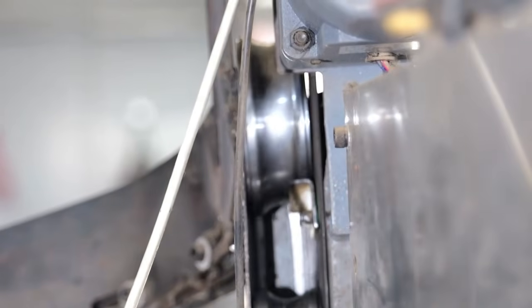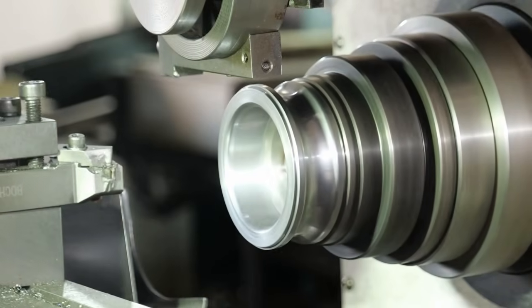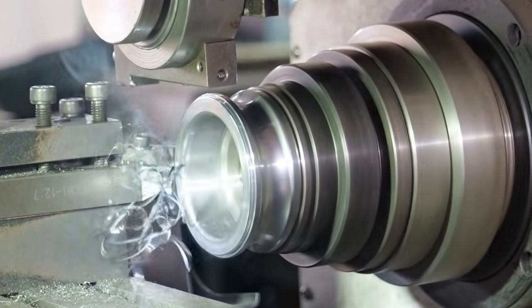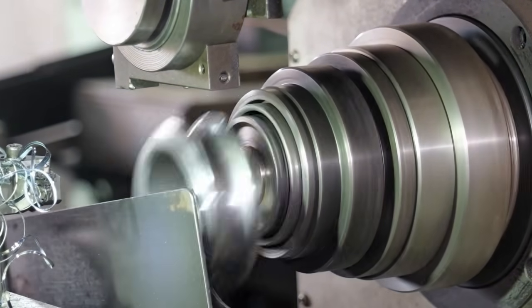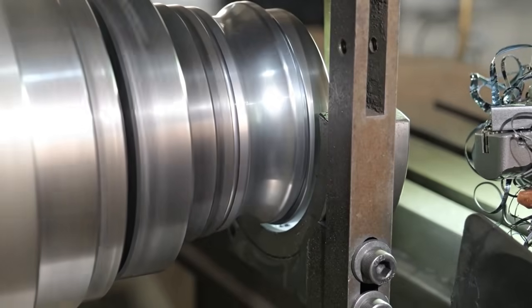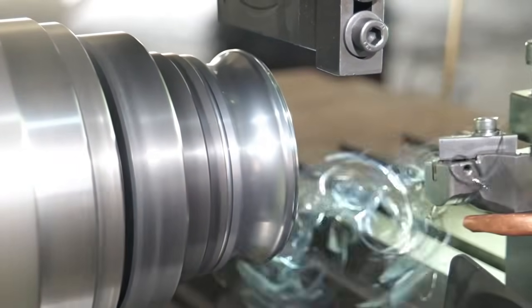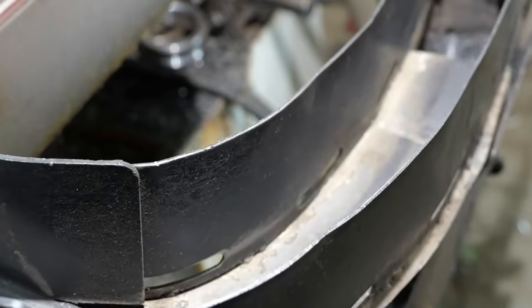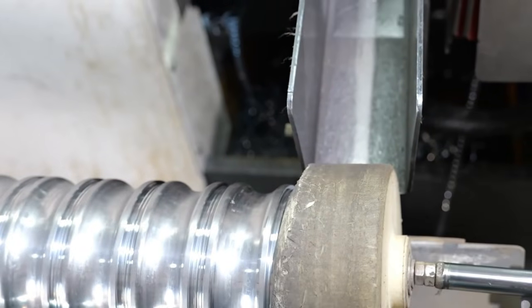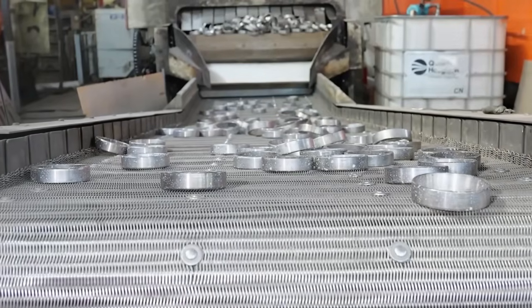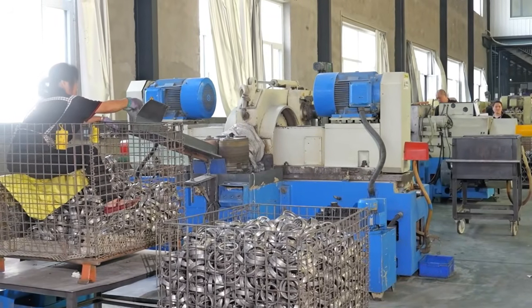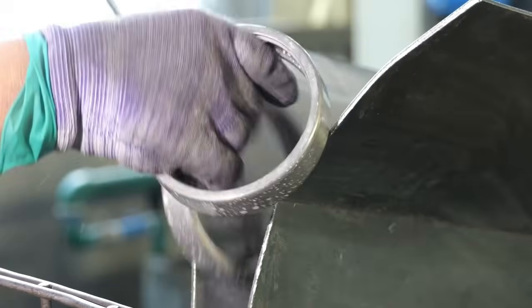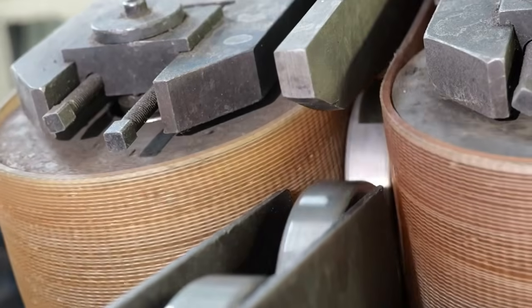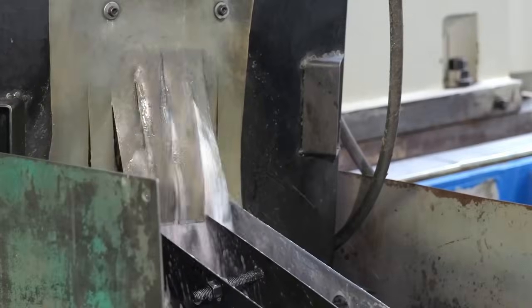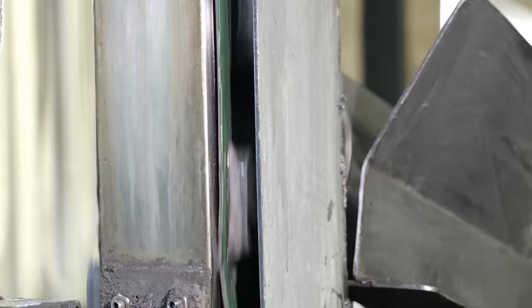The rings then move to rough machining, where the inner and outer diameters are cut close to final size, but with a little extra material left for perfect finishing later. Heat treatment comes next, heating the rings to 830 to 860 degrees Celsius, the austenitizing temperature, then rapidly cooling them to form a super hard martensitic structure. To prevent brittleness, they are tempered at 150 to 200 degrees Celsius for a few hours, keeping the hardness but